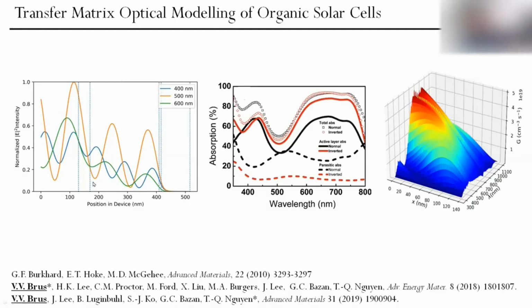So we need to know how the optical field, the strength of the electric field of the electromagnetic wave, is distributed within the active layer for different wavelengths. So we do it for all wavelengths from the solar spectrum, which is from about 250 nm until the wavelength defined by the band gap of the semiconductor, where it still absorbs. So by applying this technique, we need to know the optical constants of all layers involved in the device structure. Definitely also the optical constants of this active layer, a mixture of donor and acceptor organic semiconductors.